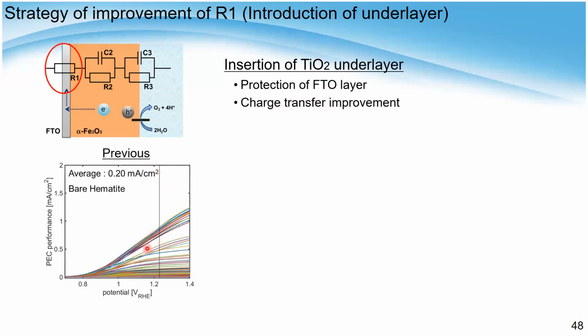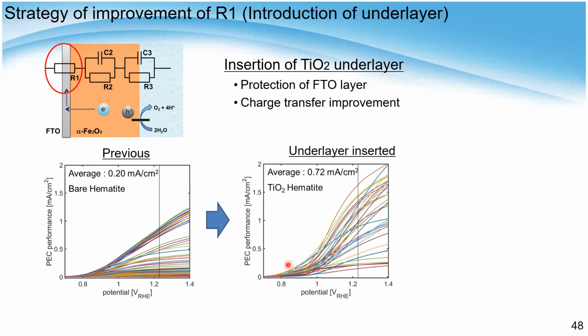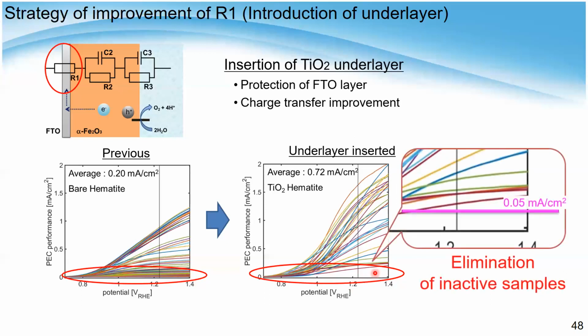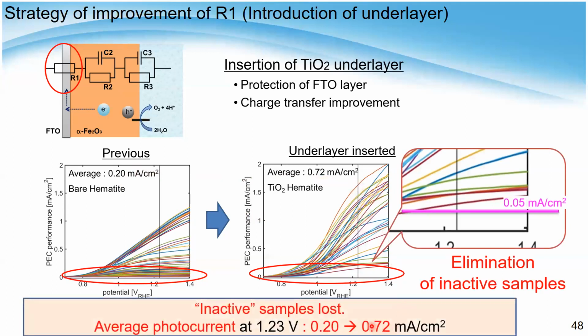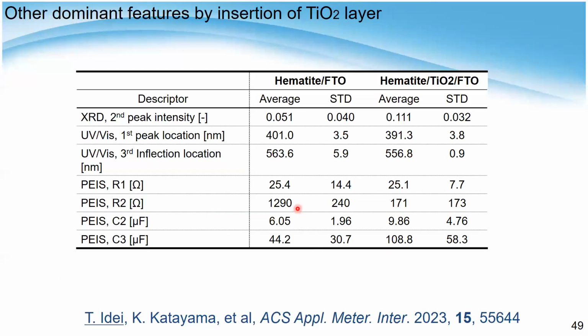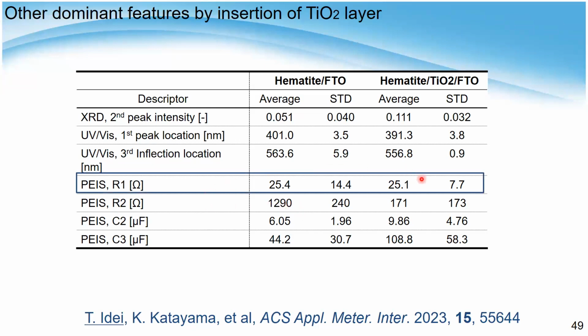And then what happened here is this is the PEC performance for the previous samples. Without a TiO2 underlayer, versus with the TiO2 underlayer, the performance is quite a bit better. And as you see, here are the inactive samples. There are so many inactive samples in the original samples, but once TiO2 was inserted, the inactive samples totally disappeared. Also the average photocurrent value is obviously much improved. So what we could learn from here is that we focused on this one parameter, and it has been improved to remove the inactive samples.